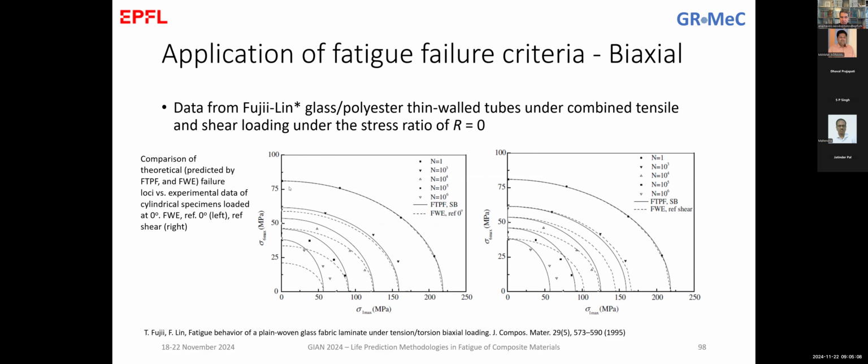And then on the other side, it predicts well for static loading, but when we start introducing cycles, we start getting inaccurate, and the more we go in life, the more inaccurate we are, with the lifetime prediction for 1,000,000 cycles being less than 100% accurate. So we have a scatter or inaccuracy in the predictions of more than 100% in this case.